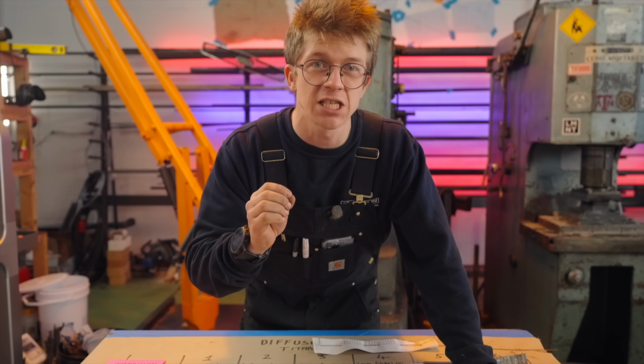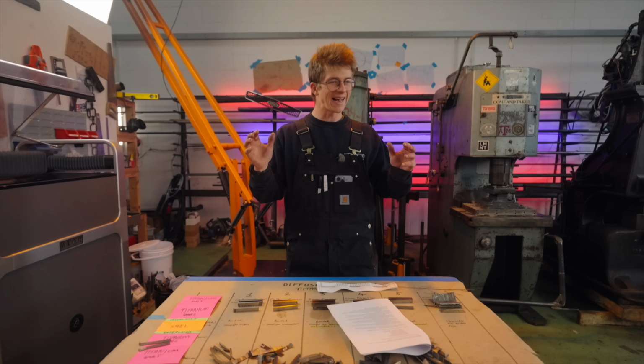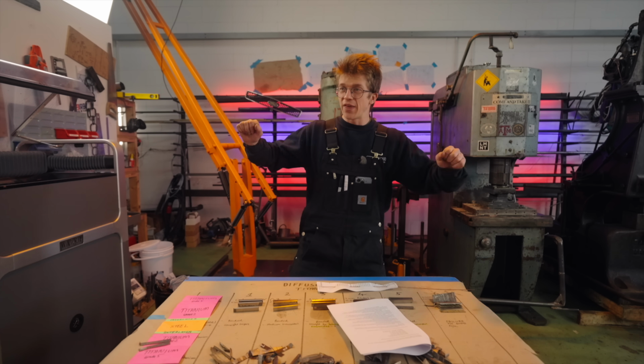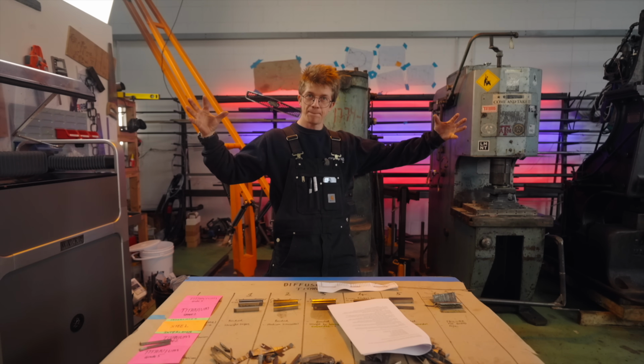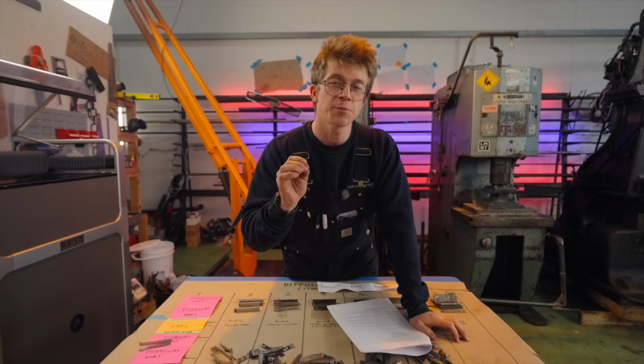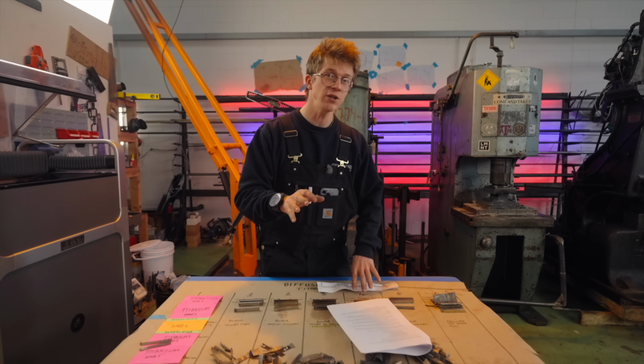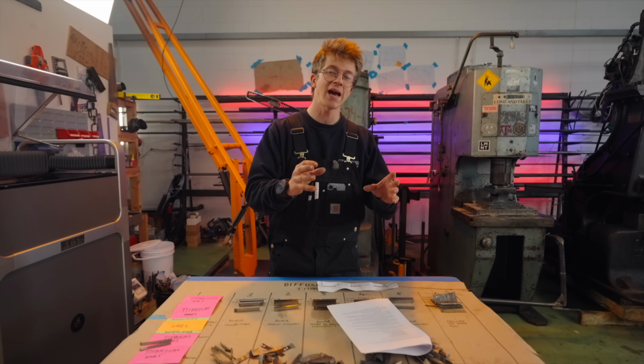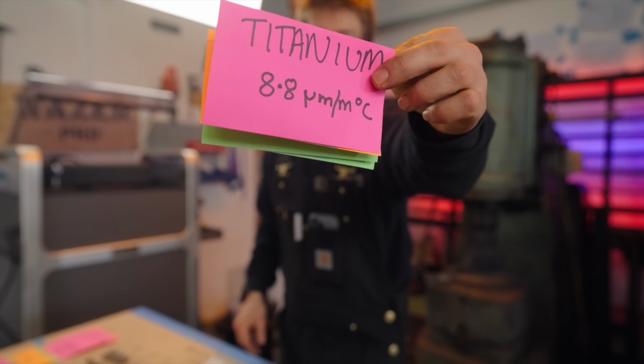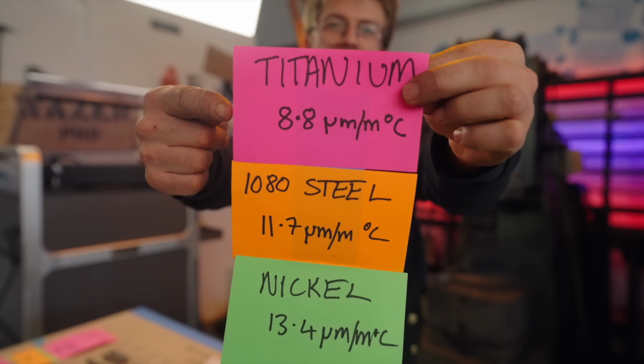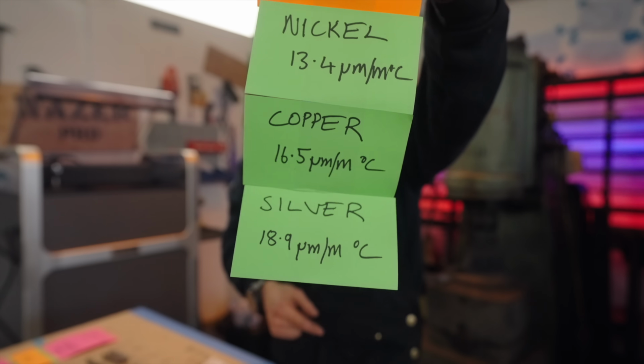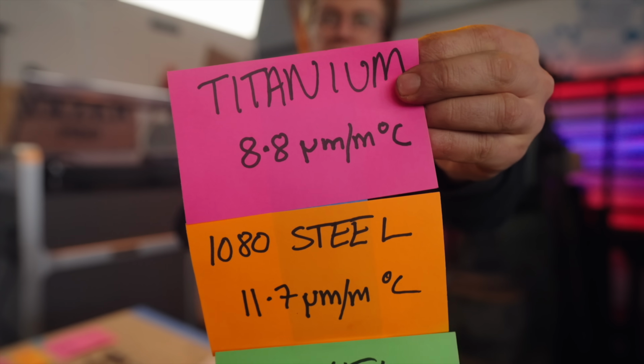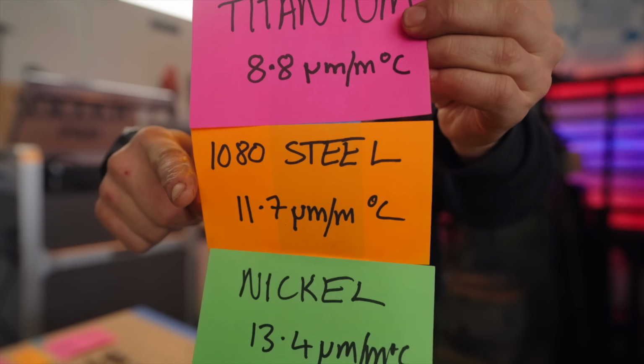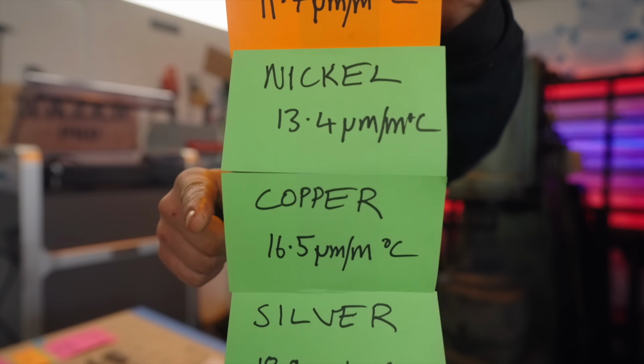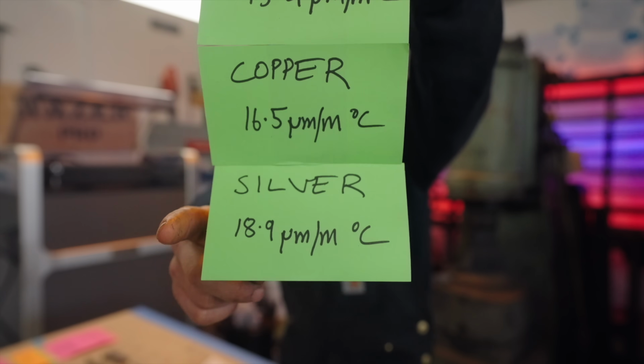Or another theory I have is that it might have something to do with the coefficient of thermal expansion. When material gets hot, atoms start having a party and they make a little bit more space, metal get bigger. But not all metals expand at the same rate. And the coefficient of thermal expansion, or the CTE, is the amount that a metal expands per degree of temperature. Check it out. Titanium has the lowest thermal expansion of all of the metals we're playing with, at 8.8 micrometers per meter per degree Celsius. 1080 steel, 11.7, nickel 13, copper 16, and the most at a whopping 19, silver.